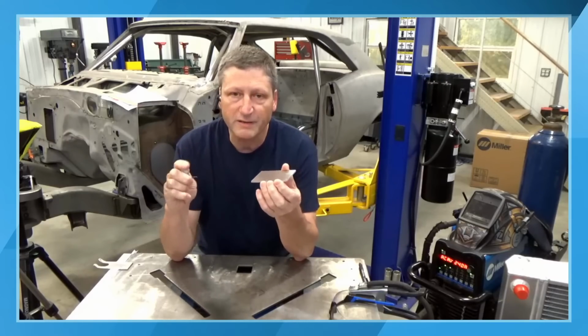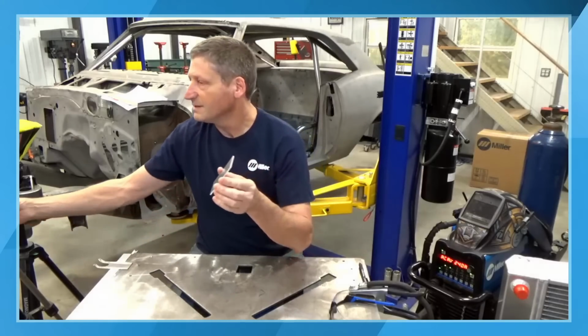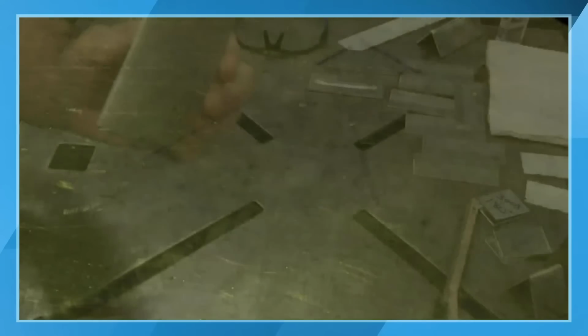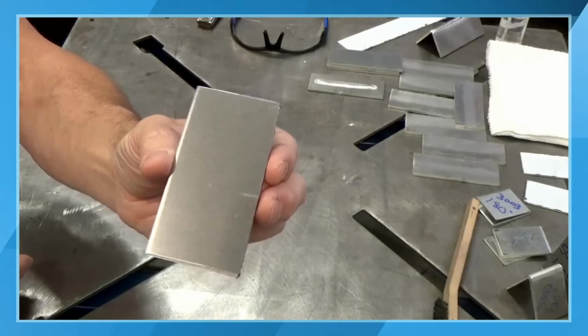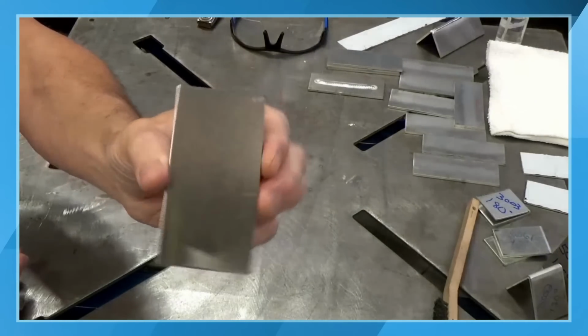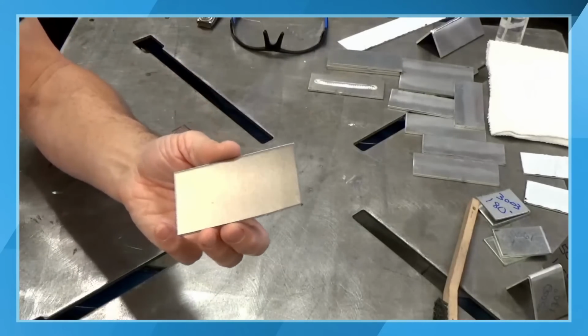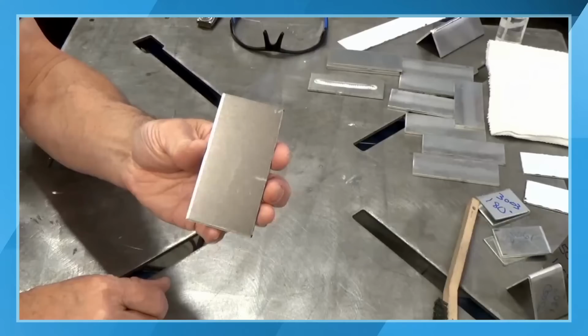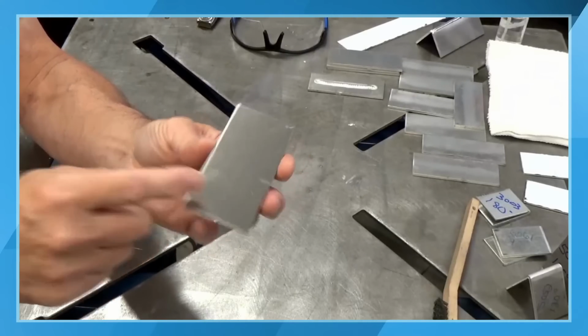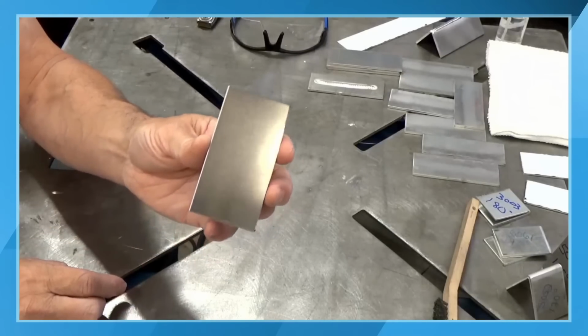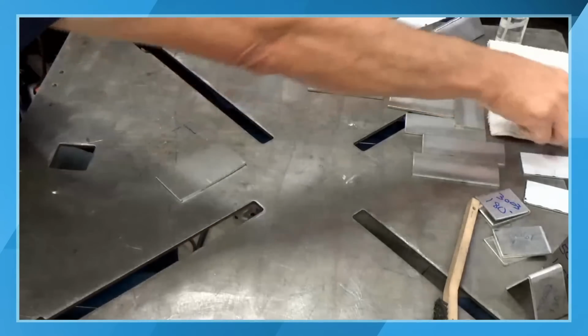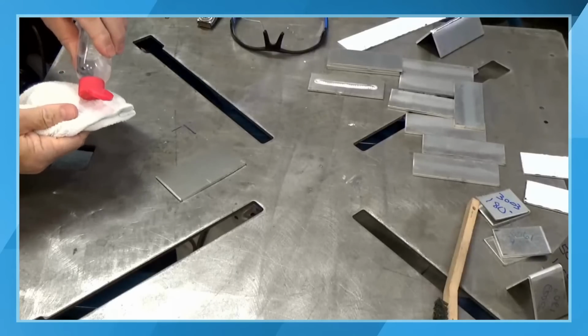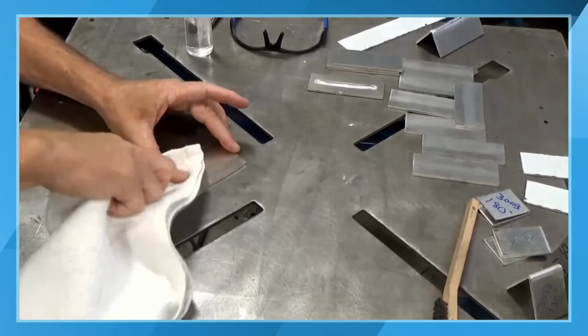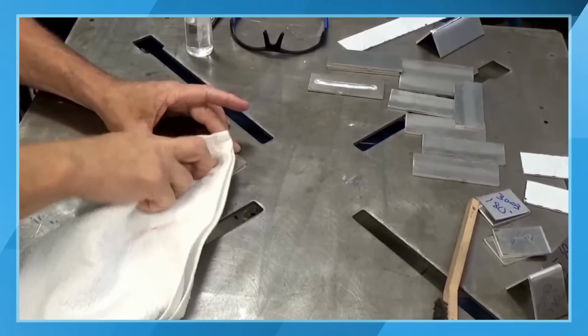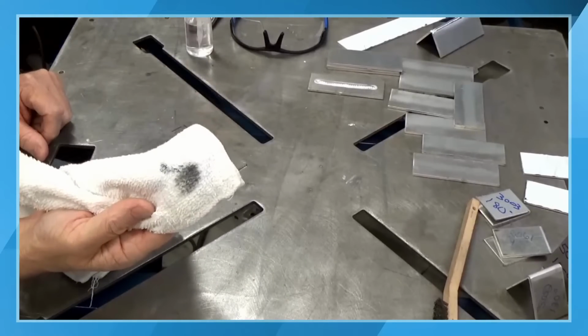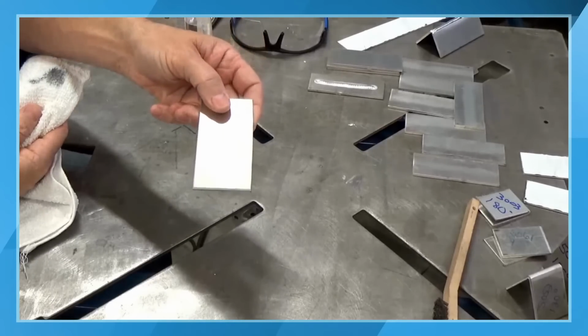So when you peel that stuff off, what you'll notice is the aluminum looks really clean underneath. I mean, that thing looks ready to weld, right? But not really. That film keeps it protected from getting scratched and stuff, but unfortunately it still does leave a residue on here, and that oxide layer is still pretty heavy on this piece. I can prove that simply by taking a little bit of acetone on a rag and you can literally wipe it. Even though that piece looks clean, look at what's coming off of that. And really it didn't change what the aluminum looked like at all.